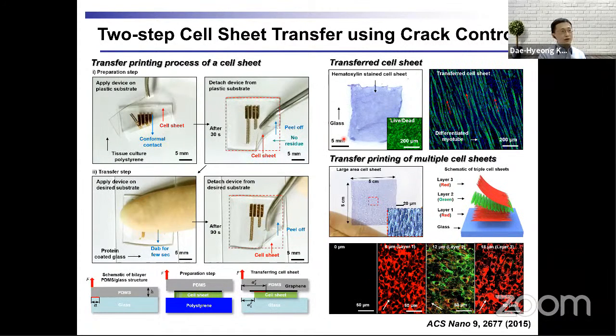We have been working on transfer printing of various kinds of nanomaterials, including silicon nanomembranes, using a PDMS stamp. Typically, we use kinetic control. But in the case of cell sheet, we modified such transfer printing a little bit. First of all, we have to culture the cell sheet on the PDMS. If you try to culture a cell sheet on bare PDMS, it is very difficult because the cell sheet cannot adhere to the PDMS surface, since PDMS has very low surface energy.